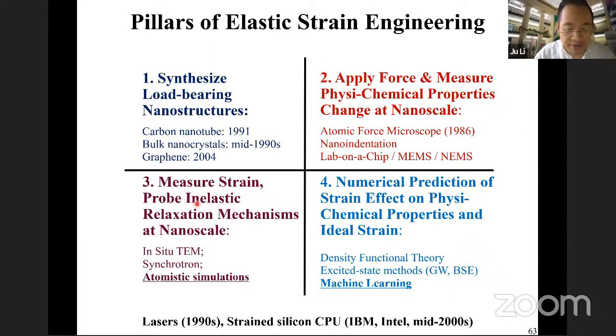Was that phase transformation? So you need this deformation mechanism studies using extended timescale atomistic simulations. So in my group, we develop those kind of methodologies to study the rare events of defects, or you use in situ TEM or synchrotron to understand the deformation mechanisms. And that was really developed in the last 20 years.